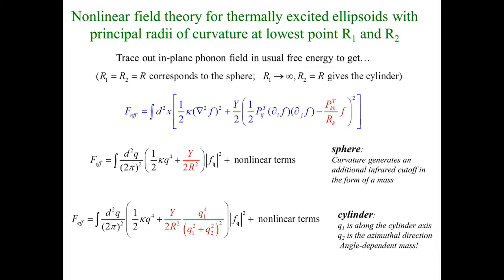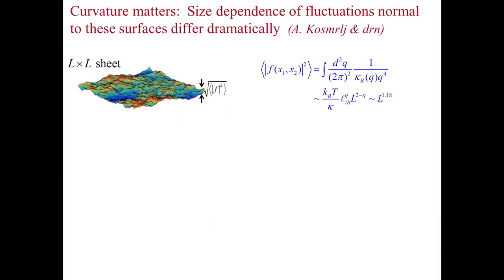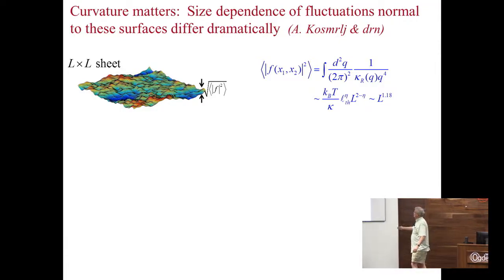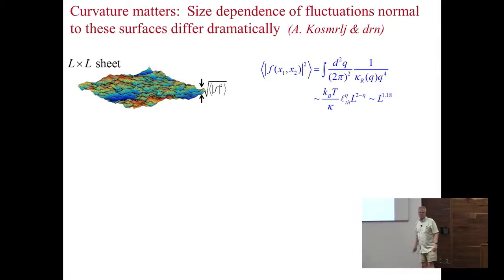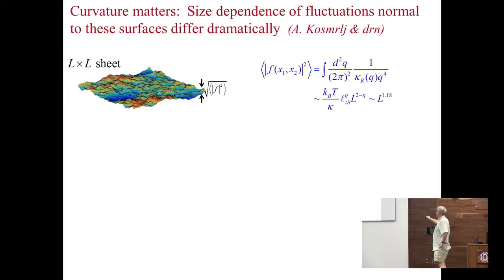Even for a cylinder, interesting things happen. For a cylinder, you get this weird looking term here, and you can think of that as an angle-dependent mass. And I'll wrap up by just saying what happens in these 3 cases to a very simple quantity, the root mean square vertical fluctuation of the sheet. How does it depend on the size? It's sort of like a Lindemann criterion, but it's the vertical flexural phonon field that I'm talking about. So for an L by L sheet, if you work that out and you use this renormalized bending rigidity that I've been talking about with the exponent eta equals 0.82, after some math, you find that the mean square fluctuations of this height scale with the system size.